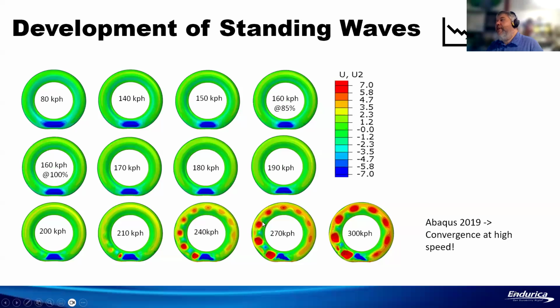So to use the damage tolerant procedure in this example, what we do is we model each of the test steps individually, right? So this is 13 different load cases, basically the tire running at speeds ranging from 80 kilometers an hour to 300 kilometers an hour. The different loads are applied here, right? The first 4 steps are 85% load, and the rest are at 100% load.